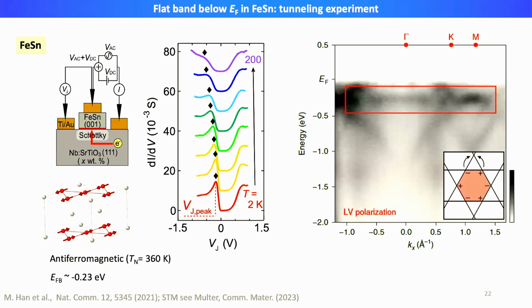And since this system is antiferromagnetic with a critical temperature around room temperature, as we warm up the system we do see a smearing of the flat band itself, and the location of this peak also moves a little bit. This suggests that as the antiferromagnetic order is weakened, the location of the flat band also moves a little bit, and there seems to be a very strong correlation between the antiferromagnetic order itself and the flat band itself. Okay, so the reason I wanted to show you this is to convince you that we're able to see these flat electronic states from multiple experimental probes.